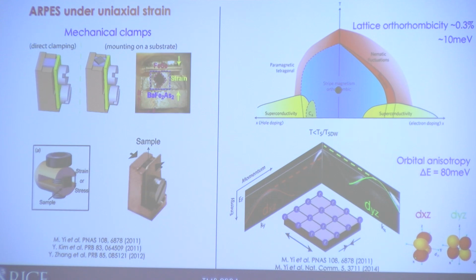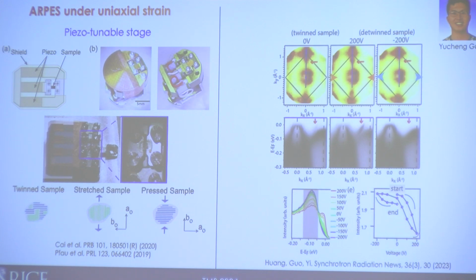Anyway, so this is the sort of early work putting strain. And that's basically a way to look at on-off effects of strain. But then, also again driven by Ian Fisher's group, folks have developed a way to actually apply continuously tunable in situ uniaxial strain by using these piezo devices. Basically, these are materials where you apply a voltage, they will shrink or expand on demand, depending on how large a voltage you apply. And this was developed by Cliff Hicks and others, where they can actually have three that also account for the thermal expansion. And then basically, by applying voltage plus and minus, you can stretch or compress the sample and then do the complete series of measurements.